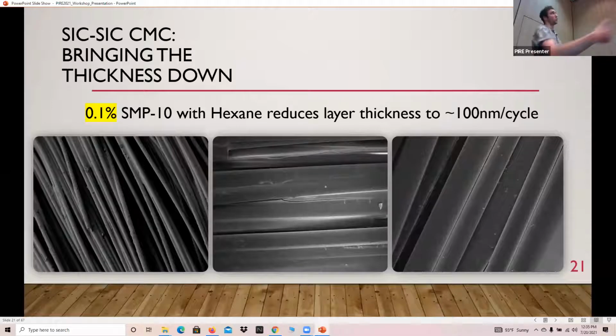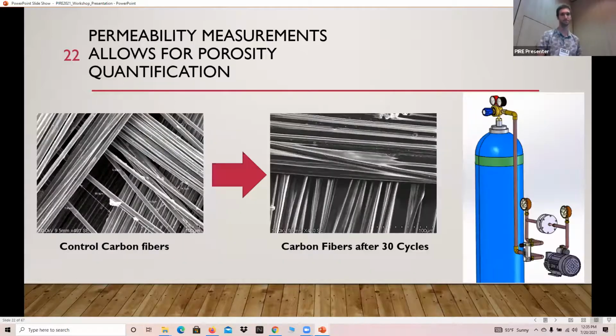And then, like I was saying earlier, we want to actually reduce the thickness that we deposit so that we can really, really accurately control the porosity, thus permeability of the system. So here are some SEM micrographs of the 0.1% SMP10 with hexane with a reduced layer thickness to 100 nanometers per cycle. So where we're at currently is measuring permeability and moving to including different actual particles into the matrix,